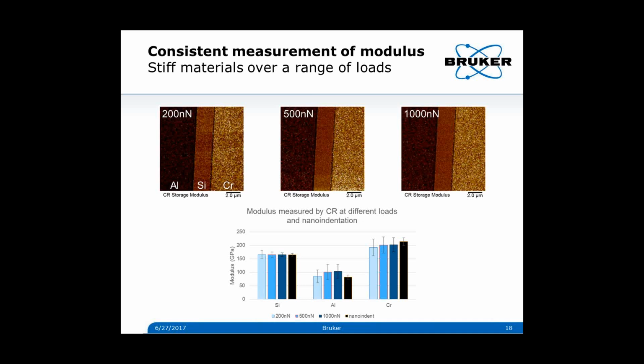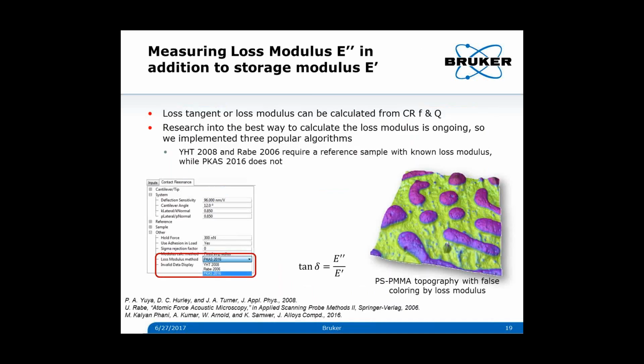This contact resonance method is really great for stiff materials. But since we already reduced the normal force and eliminated lateral forces, we can actually apply it to soft materials as well. And we can get loss modulus. Since we have the Q in the measurement and the frequency, we can calculate loss modulus and loss tangent, which are things that people have wanted for quite some time.